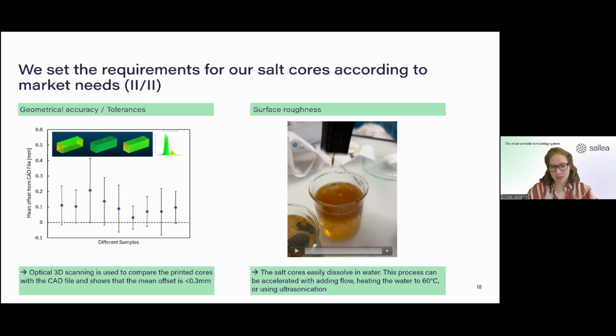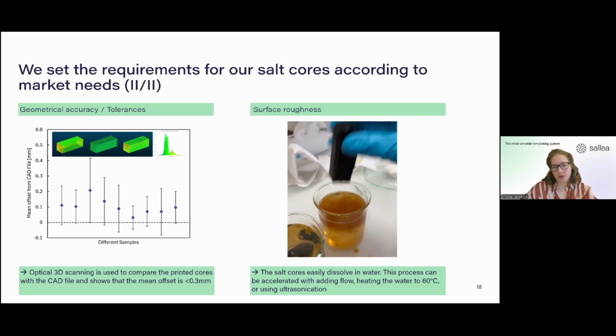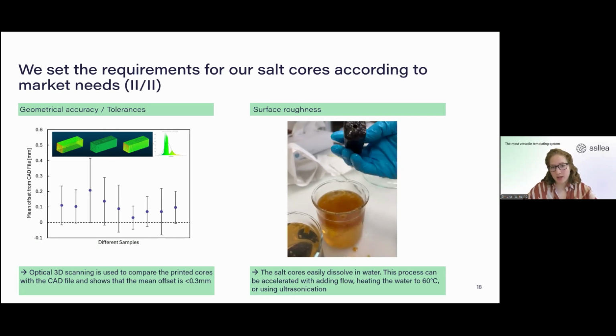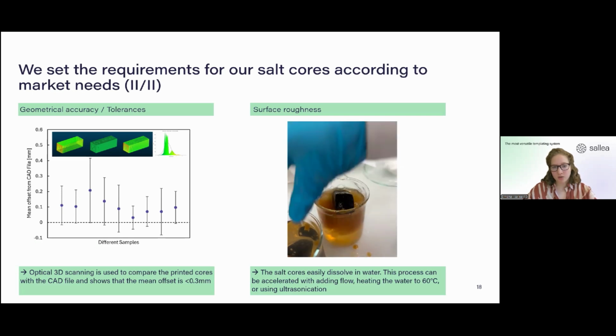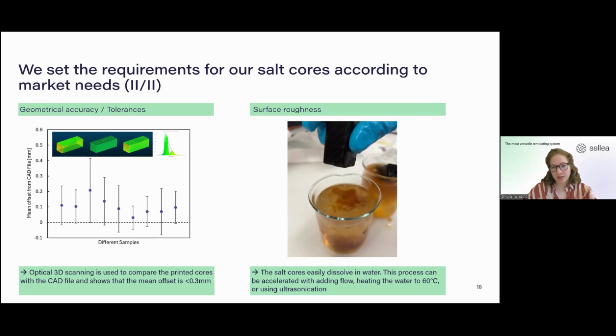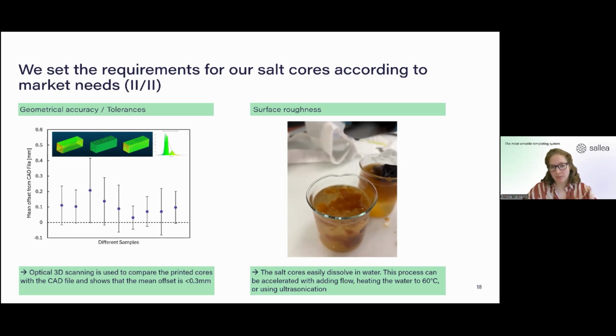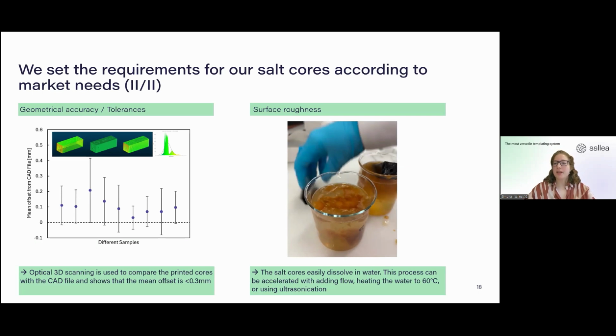And then in the video, you can see that one part has a very small opening to remove the core, and the next one has a bigger opening, and it comes out quite nicely, and over time it would even dissolve further in water. In general, to speed up the process of dissolving the salt core, you can add flow. This always helps. The water can also be heated to, for example, 60 degrees. That speeds up the process as well. And if available, ultrasonication can improve that a bit further.